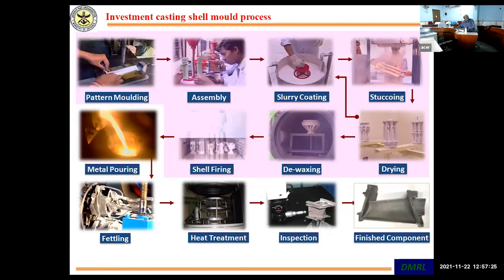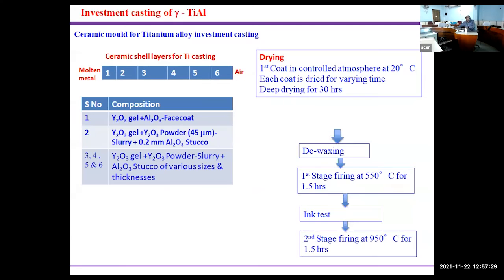Why investment casting? Because these gamma aluminides have very low ductility, so they are generally investment cast. Here we are trying to make an investment casting shell. These are Y2O3 gel plus Al2O3 face coat. So it is in the initial stages.